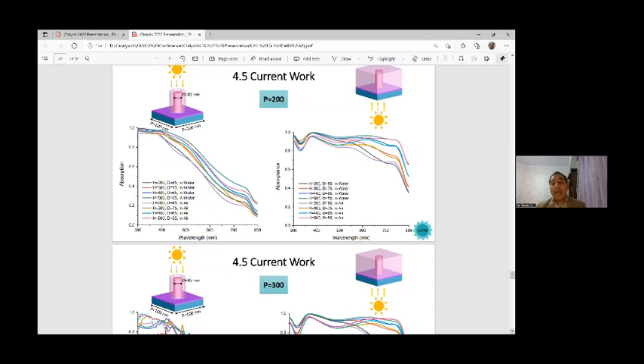It should be noted that our simulation results show that the absorption in water is higher than in air. So the water environment is better than air. So we can move to photoelectrochemical water splitting systems for this reason.